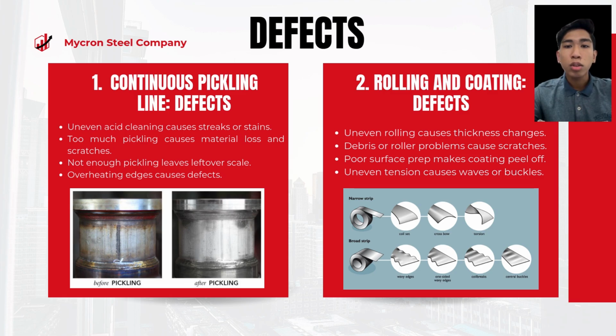Moving on to rolling and coating. Uneven rolling can cause thickness variation, leading to inconsistent product dimensions. If debris or roller malfunctions occur, they can result in surface scratches, which affect both aesthetics and functionality. Poor surface preparation can lead to coating adhesion issues, causing peeling or flaking. Moreover, improper tension control during rolling may lead to waves or buckling, making the material unsuitable for further use.